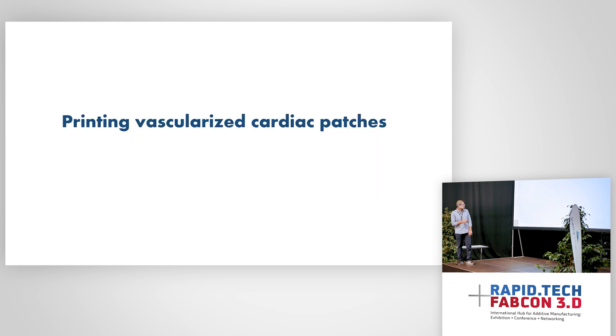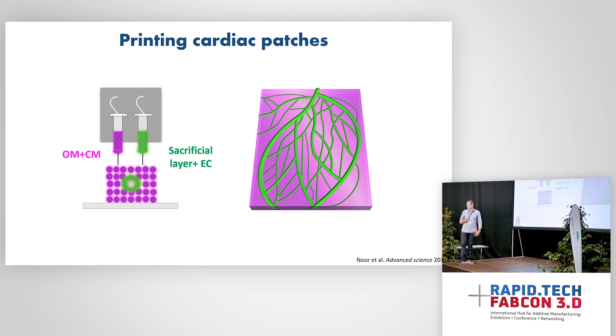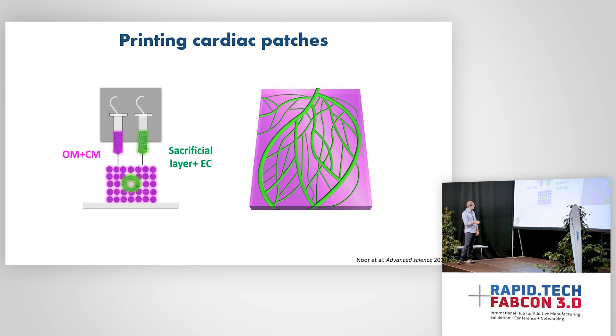This is the model we want to print. For the printing method, we used two bioinks. One is the personalized hydrogel mixed with heart cells, extruded from one nozzle. The other is gelatin — which is a stiff hydrogel at room temperature but completely liquefies at 37 degrees — mixed with blood vessel forming cells, printed in the middle of the layers. After we finish printing the patch, we warm everything to 37 degrees. The personalized hydrogel crosslinks and solidifies, while the gelatin liquefies and evacuates from the tunnels — sacrificed — leaving open tunnels. The blood vessel forming cells then completely cover the interior of the blood vessels. This is how the printing looks: an extrusion bioprinter with a 150-micron needle, alternating layers of personalized hydrogel with heart cells and gelatin with blood vessel forming cells.